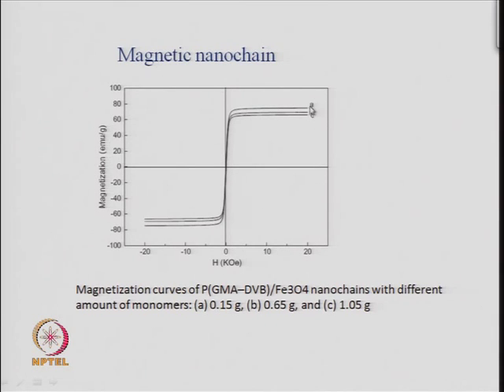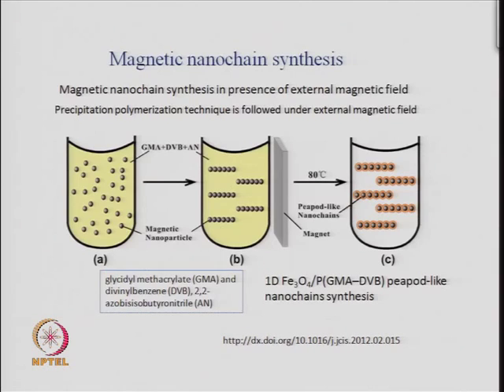So, A is a very small amount of polymerization which has taken place, and so you see the magnetization is higher, because the iron oxide can feel the applied magnetic field and its magnetization is high. When you add more of the monomer, then more of the chains are covered with the polymer. So, the magnetization decreases from A to B, and then if you further increase the monomer, the magnetization decreases further to C. So, effectively with the change in the thickness of the polymer around the particles, if you increase this polymer which is forming, by increasing the amount of monomer you are adding, you will decrease the magnetization, and that is what is happening.